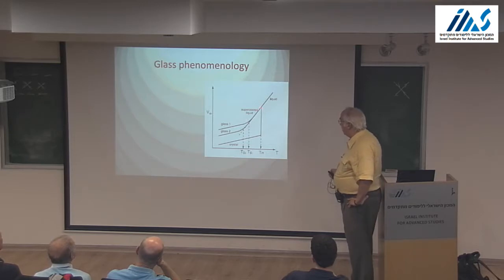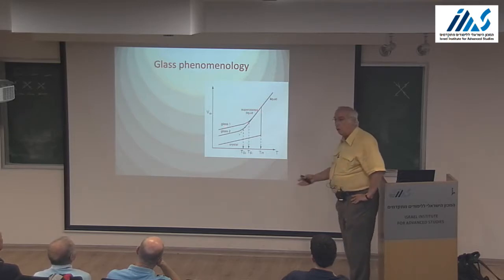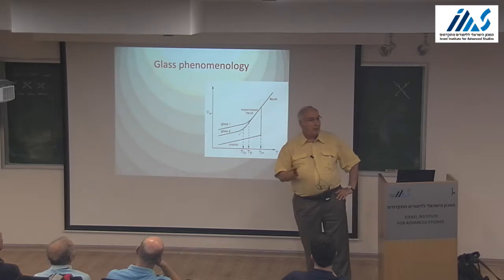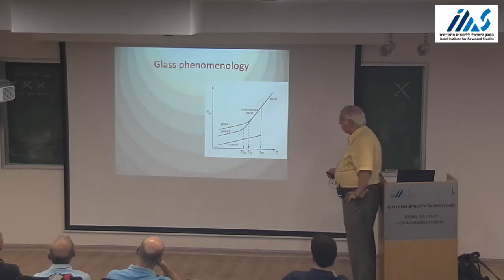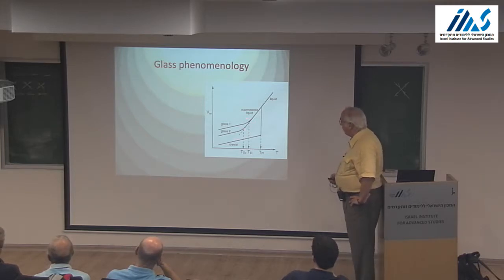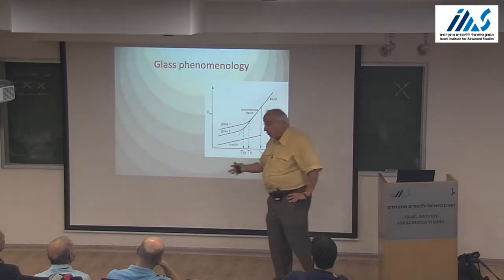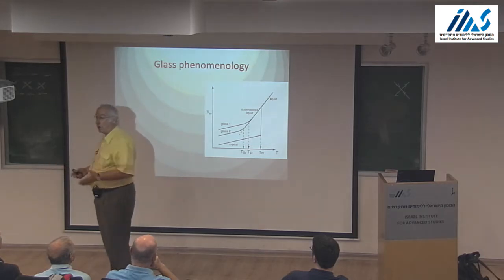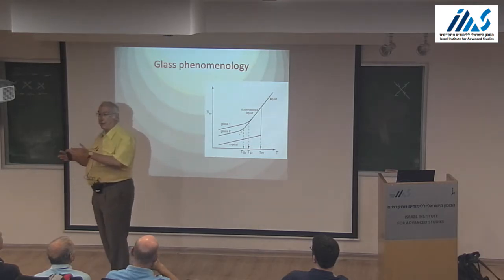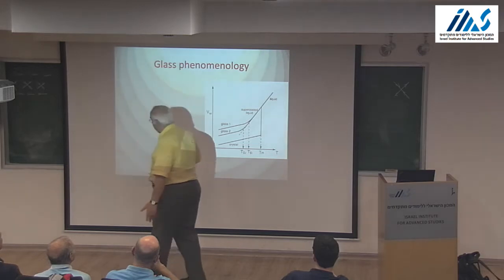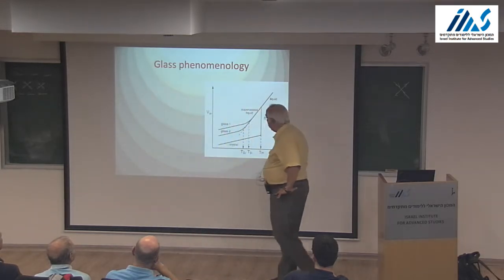When you go to the supercooled regime and continue to cool, there is what we call the glass transition, which is a somewhat ill-defined concept because the glass transition depends on the protocol. Do you do it slowly or rapidly? But the point is that at some point, the specific volume as a function of temperature has the same slope as the one of the crystal, and indeed, the material becomes solid. What does it mean to become solid? Well, we know the difference, right? When you put a strain on a fluid, it flows. When you put a strain on a solid, there is an elastic response and it doesn't flow. So this happens.